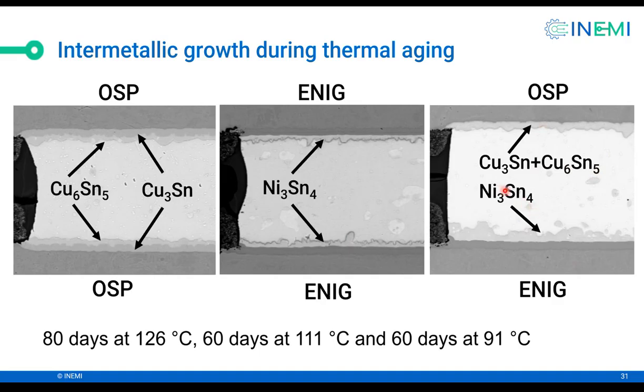So now let's do electromigration. Oh, before I go there, the question would be, at what temperature did we do this thermal aging and for how long? The answer is, the first 80 days we were at 126 degrees C, the next 60 days at 111, and the third 60 days at 91. So these samples saw all these different temperatures, right?